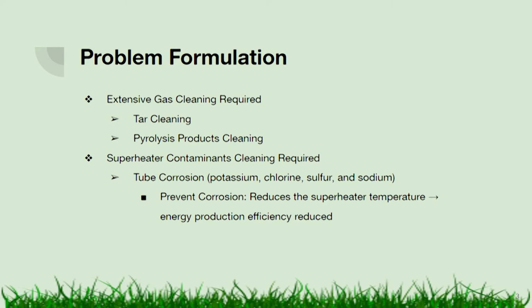Contaminants such as potassium, chlorine, sulfur, and sodium, which are often contained in biomass fuels, can deposit on superheater tubes after being exposed to combustion exhaust gases. These deposits in their molten state can lead to accelerated corrosion of the superheater tubes, thus decreasing their efficiency faster. In order to reduce the corrosion of the superheater, the temperature of the process is reduced. However, doing this leads to a lower energy production efficiency.